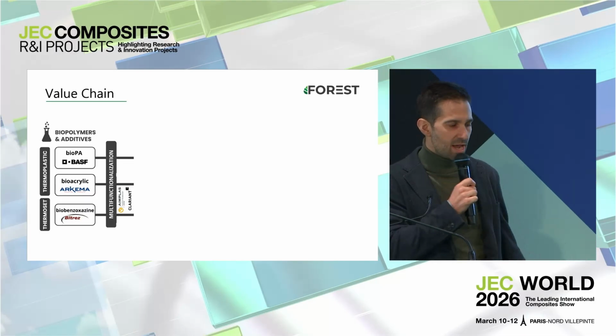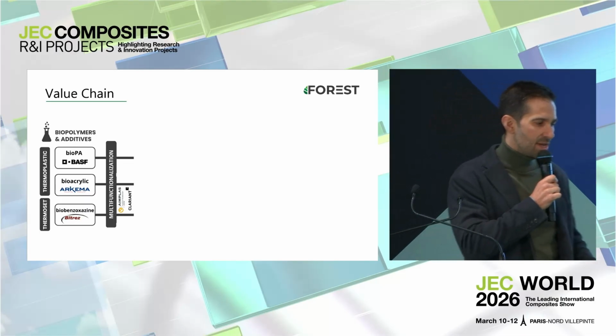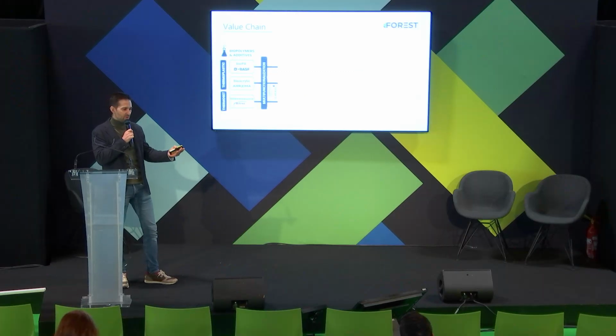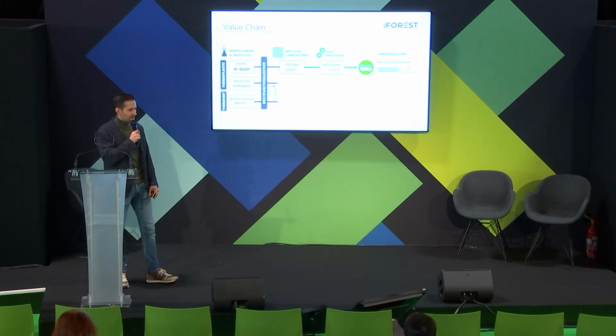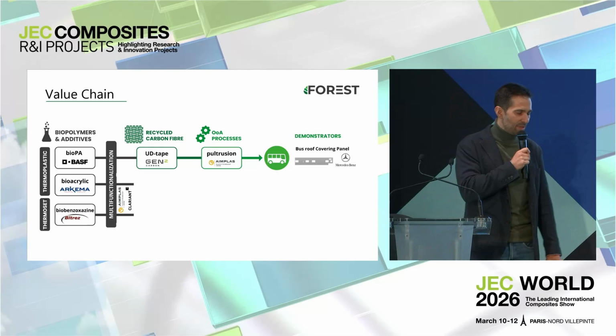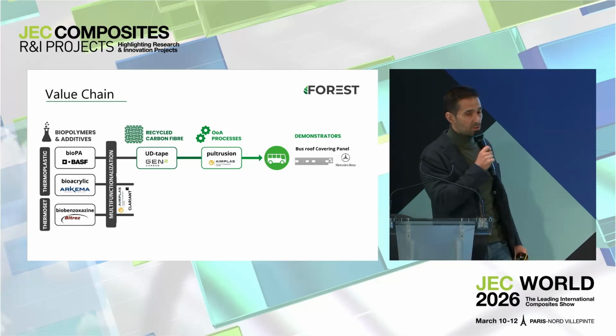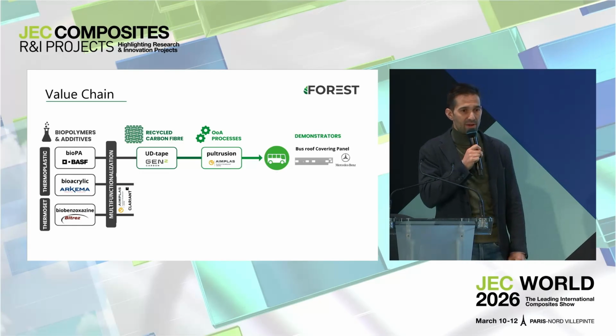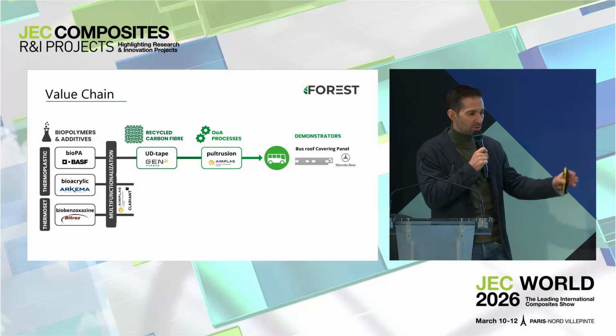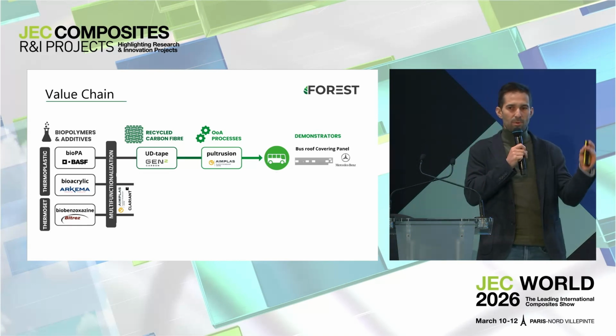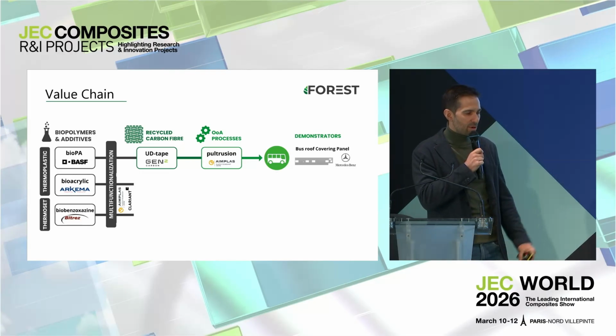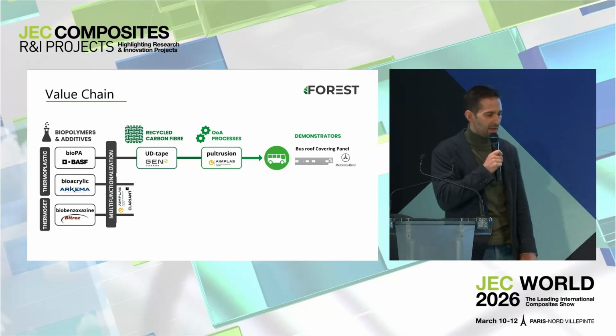And all these three resins are combined with functional additives in order to obtain different properties. This multifunctionalization has been performed mainly by AIMPLAS and Clariant. And the first resin, the bio-based polyamide, has been used for the first demonstrator. This resin has been mixed with fully recycled unidirectional carbon fiber recovered by Gen2Carbon in order to manufacture UD tapes. And then these UD tapes have been used in a thermoplastic pultrusion system to manufacture this flat profile for the bus roof covering panel demo for Mercedes in Turkey.